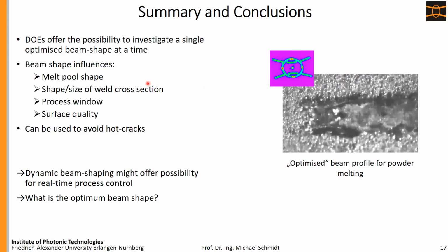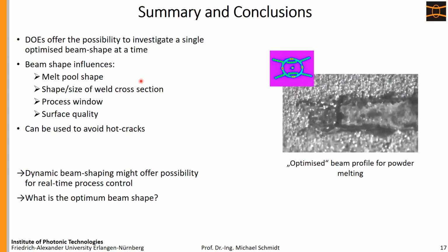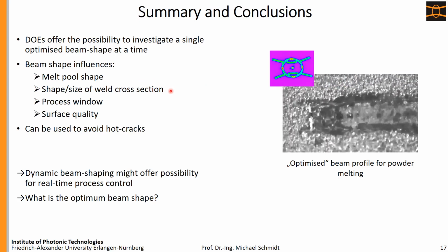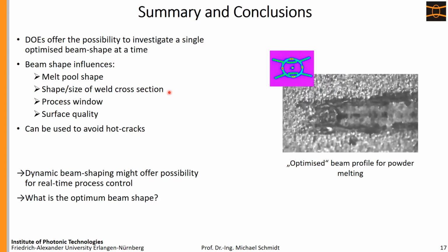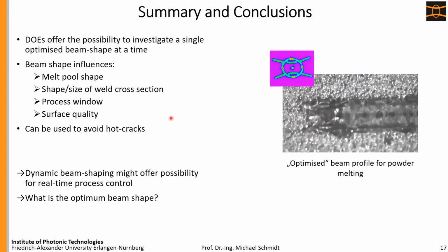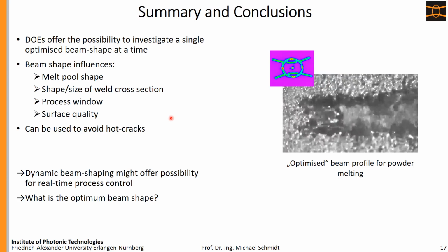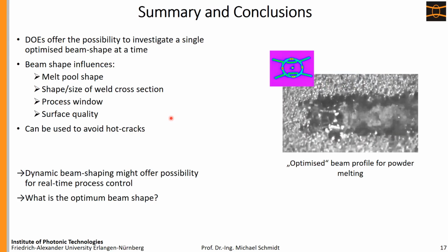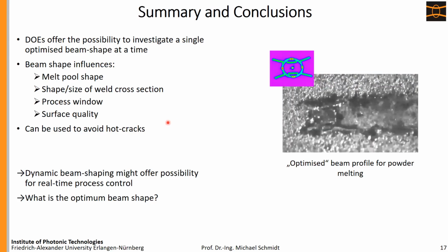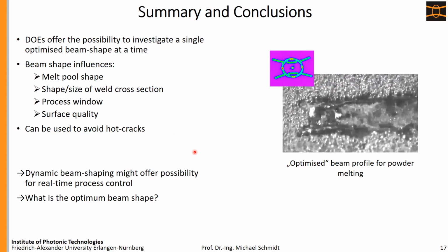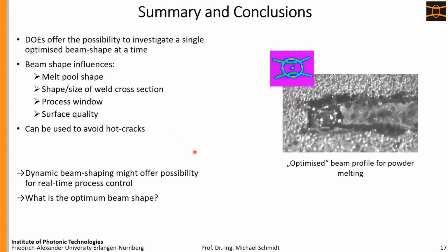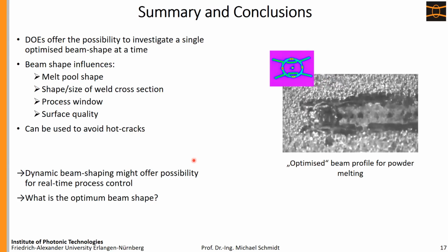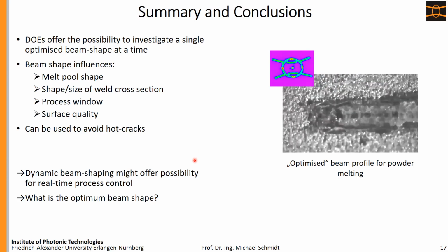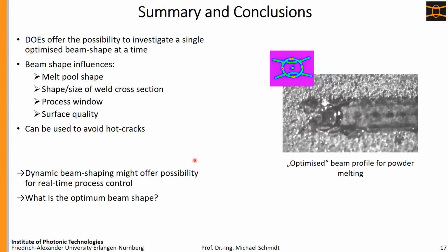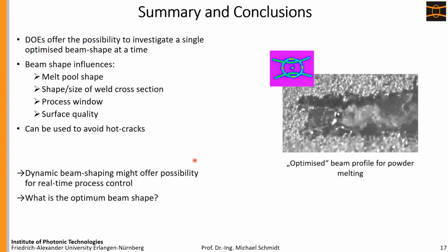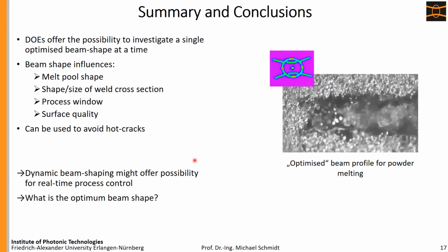As we have seen in the last minutes, we can influence the molten pool shape, the cross-sectional molten area, the process window, and the surface quality by changing the intensity distribution. This also means we can use it to avoid hot cracking. What we didn't do yet, and what we have to do and will do in future, is apply dynamic beam shaping to have real-time control over our process, and also to find out the optimum beam shape depending on the current conditions of our process.